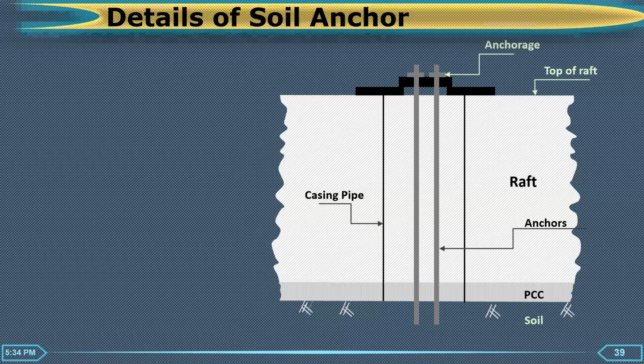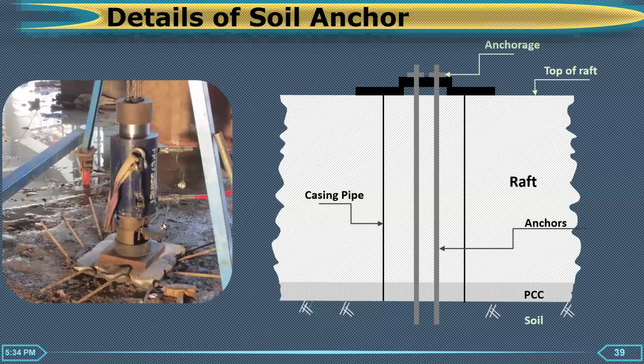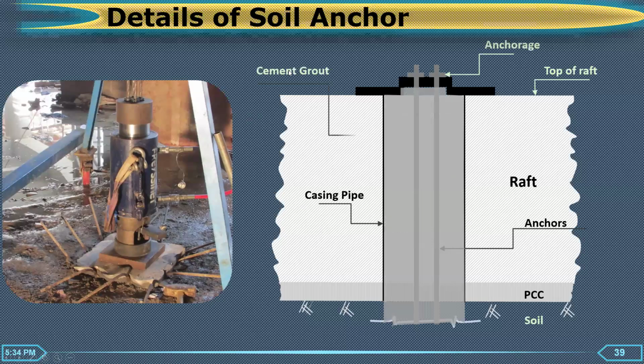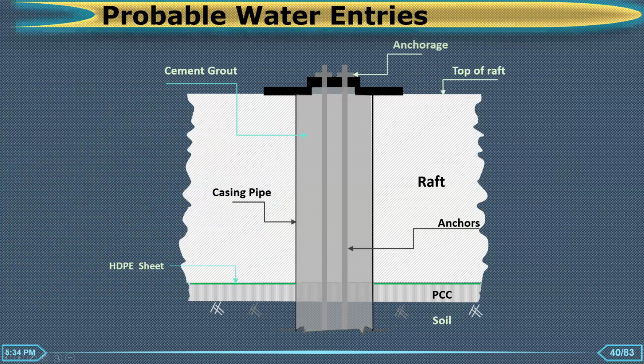Now, there are many possibilities that water enters through this interface. You can see the photograph here. It is being pre-stressed before anchoring to the top of the raft. And after pre-stressing, the cement grout is provided within the space of the casing pipe. Now, what are the probable water entries? Before detailing, we have to see the probable water entries in this interface. First of all, water can enter through the cement grout. Secondly, water can enter through the joint where the casing pipe and the waterproofing sheet meet. This is a very vulnerable joint where water can easily enter. And thirdly, it can enter through the interface of concrete and the casing pipes. So all these points have to be detailed out to best prevent the water movement within the raft.